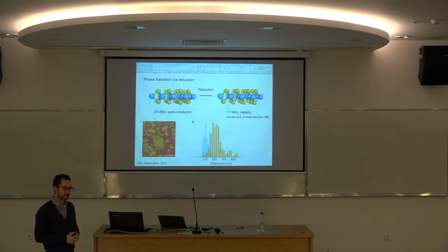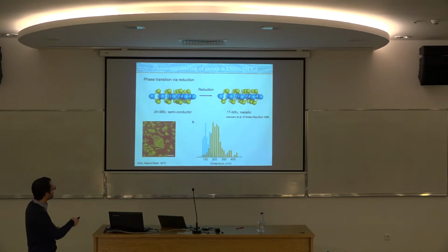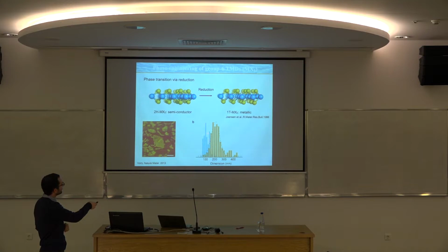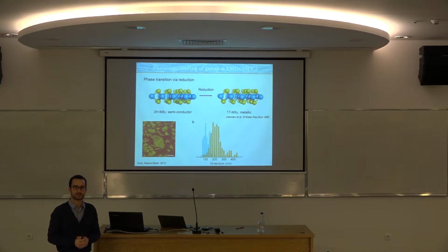which is coherent with a single layer of the nanosheets, because this is chemically exfoliated, so we still have some water trapped between the nanosheets and the substrate. If you look at the size dispersion, the nanosheets are around 200 nanometers in length. This is the length, and this is the width of the nanosheets. So you see we have a kind of Gaussian distribution of the length of the nanosheets.